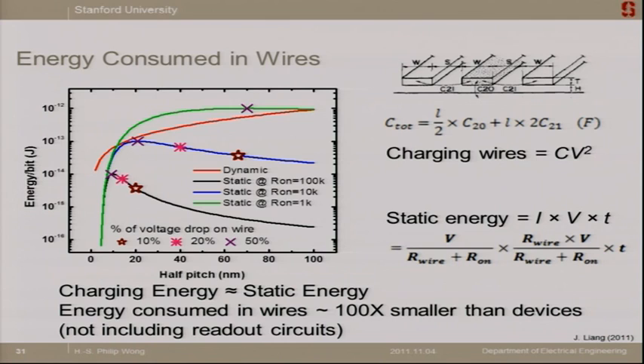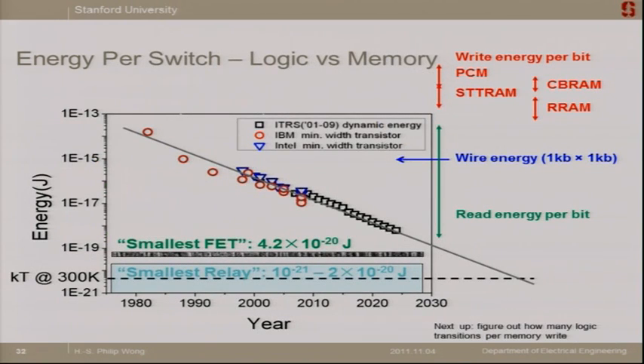These points demarcate where, towards the left of it, these curves are not valid because you have so much IR drop that you cannot write the cell anymore. So the net of that is that the static energy and the dynamic energy are somewhat comparable when you have a low on-state resistance. When you have a higher on-state resistance of the memory cell, then the static energy is not that important.